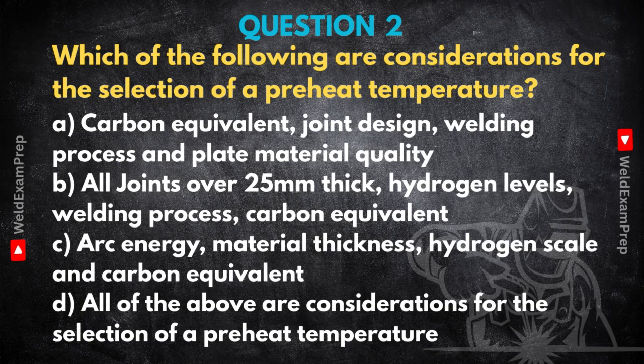Hydrogen. That's the big one for cracking, right? Yeah, exactly. Hydrogen-induced cracking, or HICC, is a major headache. Preheat helps hydrogen escape before it can cause trouble. And thirdly, it reduces the temperature difference between the hot weld and the cooler base metal, which minimizes residual stresses and distortion. Less stress, less warping. Okay, slow cooling, hydrogen removal, stress reduction. Got it. So looking back at the options, which set of factors best covers those goals?